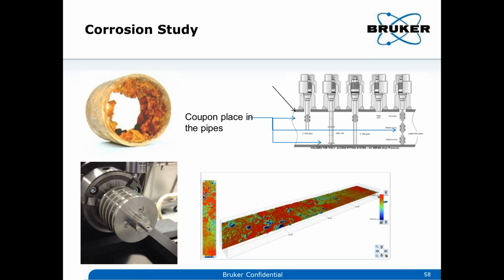And if you have an oil pipeline or a gas pipeline, you have these things called coupons, right? If you want to check whether corrosion happens in the pipe, you don't take out the whole pipe, so you have these coupons inside at certain places. So you take out these coupons. These coupons are something like cylinders sitting inside the pipeline, and then using an NPFLEX system, you can measure the whole surface and stitch it together, right? Then you can open it up and see all these corrosion pits that happen, and you can measure the volume of the corrosion, how much the surface area increased, and judge whether the pipe is still functional or needs to be replaced, right? Those kinds of things we can calculate on the live system.